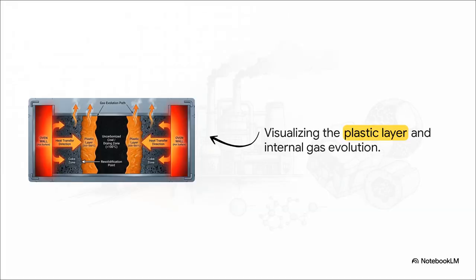If you visualize what's actually happening inside the oven, notice the uncarbonized center. Flanking it are these molten plastic layers at 350 to 500 degrees. As heat transfers inward from the superheated oven walls, this plastic layer slowly creeps toward the center, while the volatile gases escape upwards, leaving behind the solid coke zone on the outside.